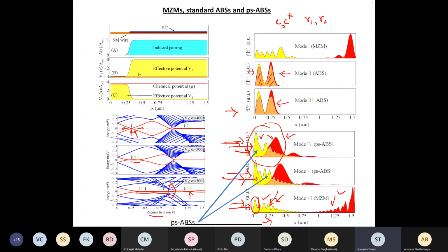And it's a very simple experiment. You somehow manage to use surface probes, and you find nodal and nodeless characteristics. For example, in muon spin rotation measurements, you measure the magnetic moment associated with the Cooper pair. If you find magnetic moments associated with Cooper pairs, then that's p-wave superconductivity. So particularly in strontium-intercalated bismuth selenide, there is evidence to show that px plus ipy is realized.